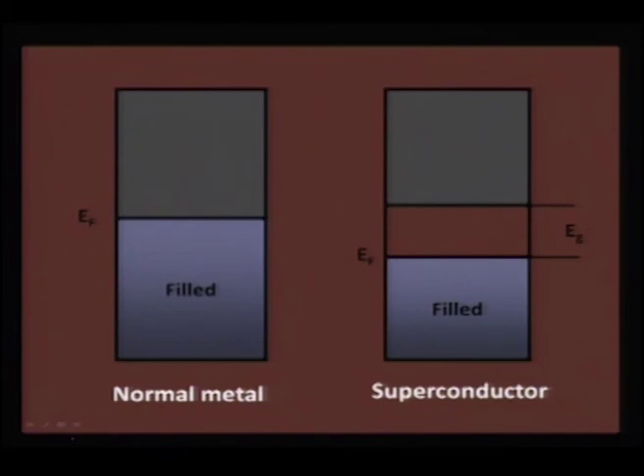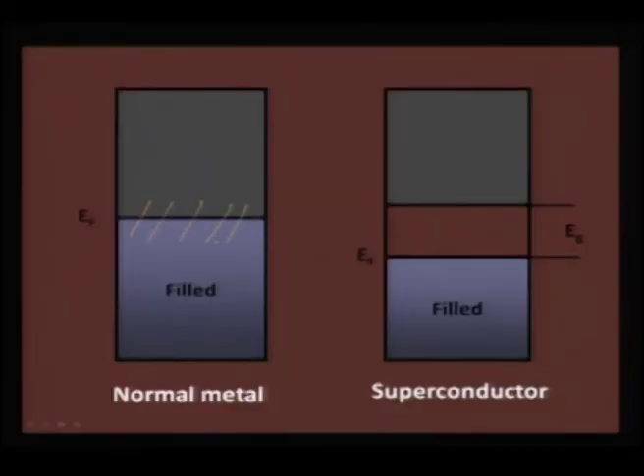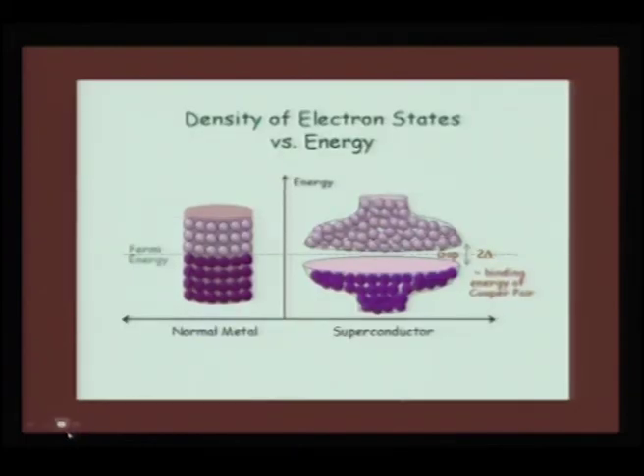And one way to identify how this differs from a normal metal is that there is no band gap in the normal case, whereas in the superconducting case, because a Cooper pair has to form, there is an opening of a band gap, which is called Eg, and once that is taken care of, then you can get the superconducting state. So, compared to a normal metal, how do we identify a superconductor? This amount of 2 delta is a narrow band gap opening, which is the binding energy of the Cooper pair. Once this is formed, the binding energy of the Cooper pair will sustain the supercurrent. So, the opening of a band gap between the valence and conduction band, compared to a normal metal, is in essence the